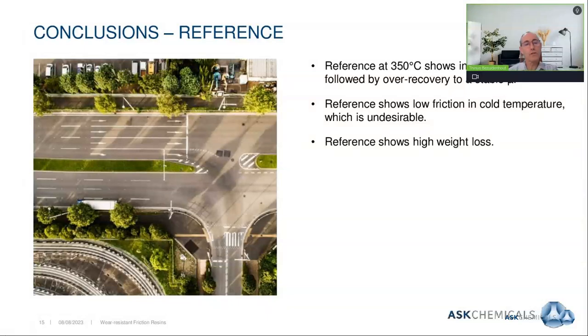Finally, we want to draw a few conclusions in each case for this comparison. If we look at the older technology, we saw in the cross testing at high temperature green fade, and we saw over recovery. And also in colder temperatures, we saw a low friction coefficient. This kind of behavior, or a fade of green fade followed by over recovery, is an undesirable performance and not up to standard or requirement. We also saw a relatively high weight loss or wear with the older technology.